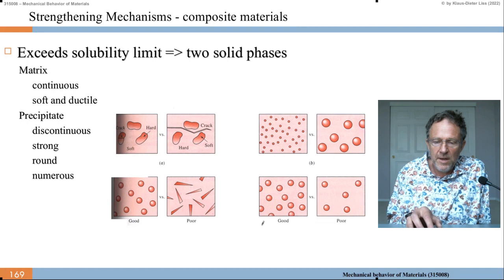Or here we have the size of the precipitates. So we have good properties if we have small precipitates and many of them, as compared to large precipitates and not so many. Or if you compare this, more precipitates of the same size may give you good properties rather than just a few precipitates.